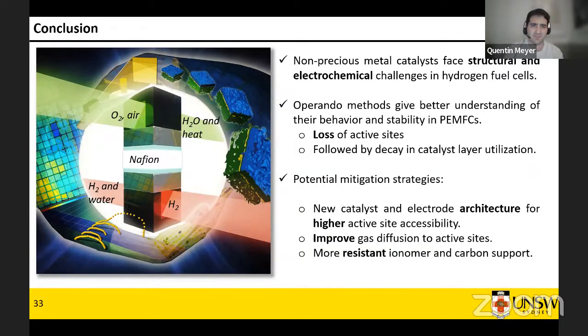This is potentially tempting. The side effect of this is if you haven't solved the degradation mechanism, you may end up with something that degrades even faster because you have more active sites, they're accessible, and they will die, all of them right away. We've seen some very nice papers in the field with a durability of 40 hours, and the catalyst held the record for a few years of being the highest performance. The other way is to improve gas diffusion to active sites. You can tweak the property of your diffusion medium to improve gas diffusion and limit water management, water flooding.